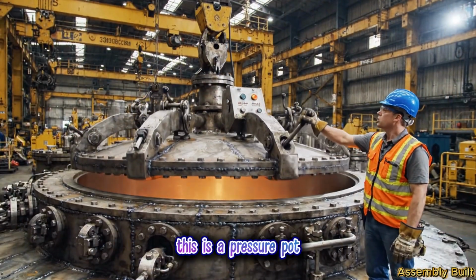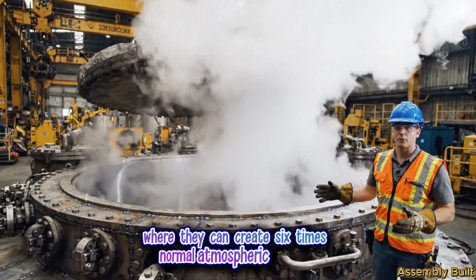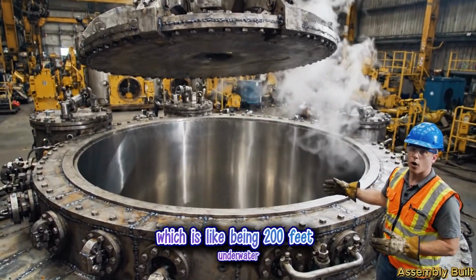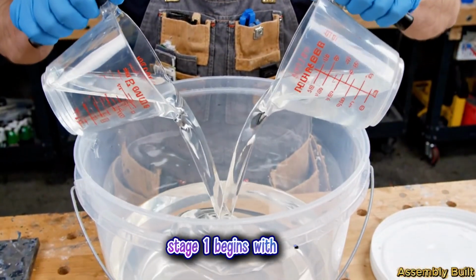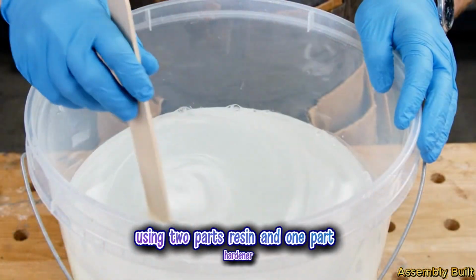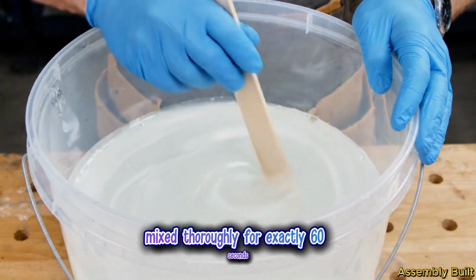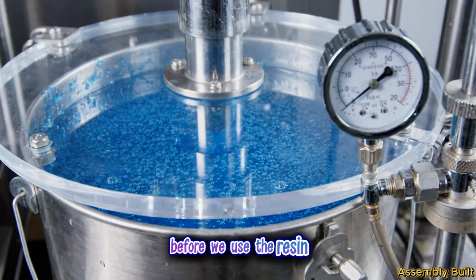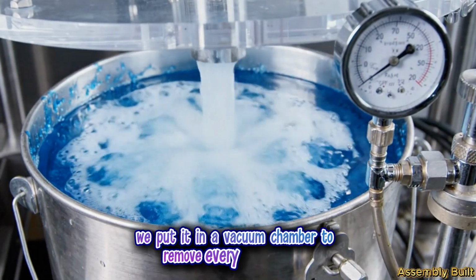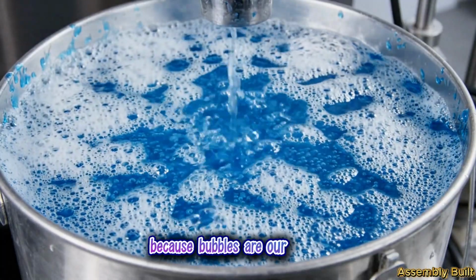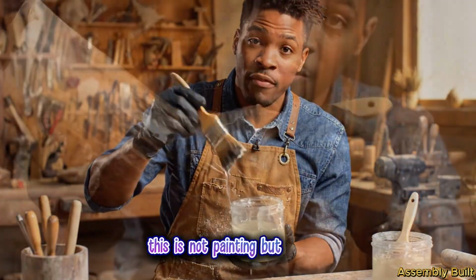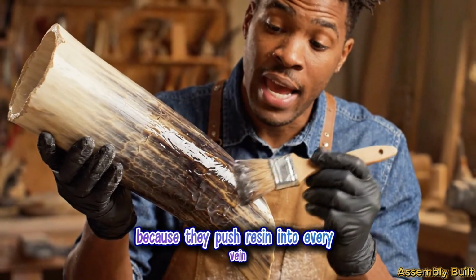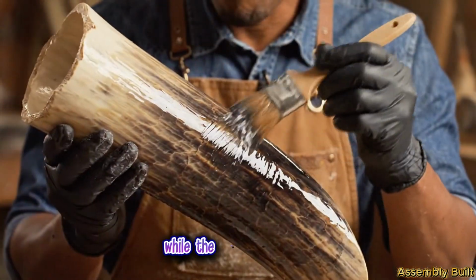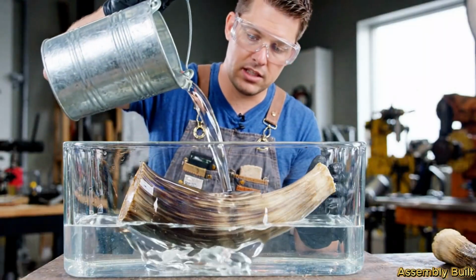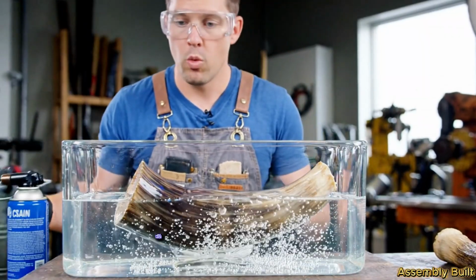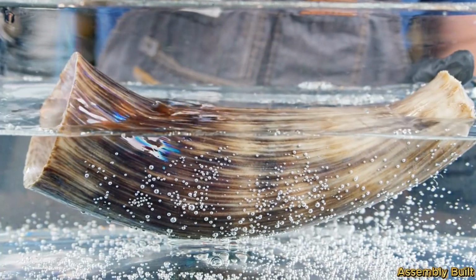This is a pressure pot where they can create 6 times normal atmospheric pressure, which is like being 200 feet underwater. Stage 1 begins with resin, using 2 parts resin and 1 part hardener, mixed thoroughly for exactly 60 seconds. Before we use the resin, we put it in a vacuum chamber to remove every single bubble, because bubbles are our enemy. This is not painting, but infusion, because they push resin into every vein, every crack, and every tiny hole while the horn drinks it in. They submerge it completely, so every square millimeter must be covered, with no air pockets and no dry spots.